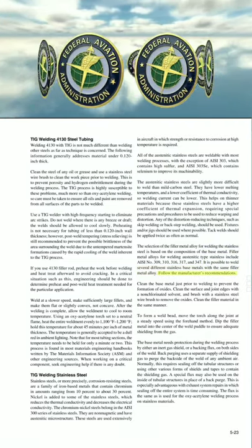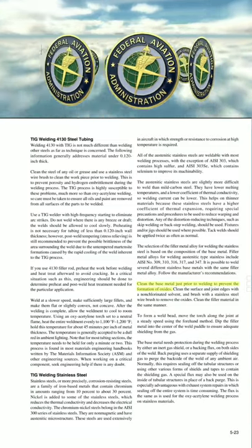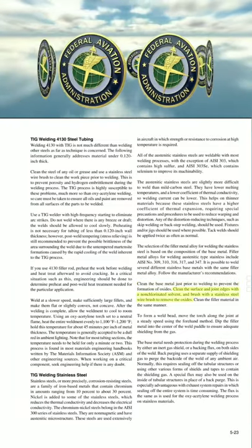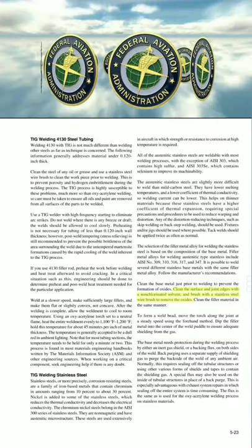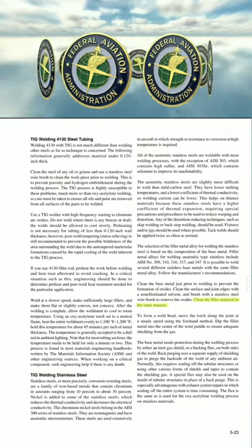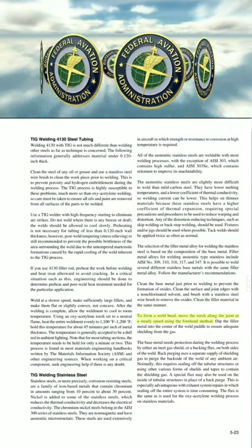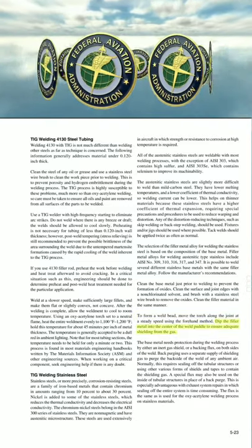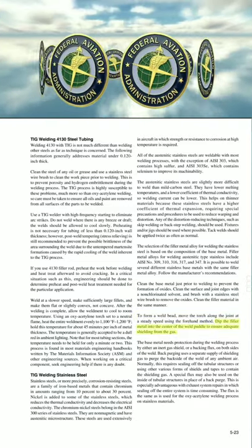Follow the manufacturer's recommendations. Clean the base metal just prior to welding to prevent the formation of oxides. Clean the surface and joint edges with an unchlorinated solvent, and brush with a stainless steel wire brush to remove the oxides. Clean the filler material in the same manner. To form a weld bead, move the torch along the joint at a steady speed using the forehand method. Dip the filler metal into the center of the weld puddle to ensure adequate shielding from the gas.